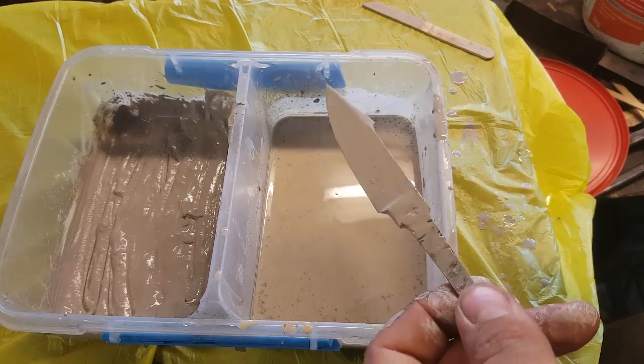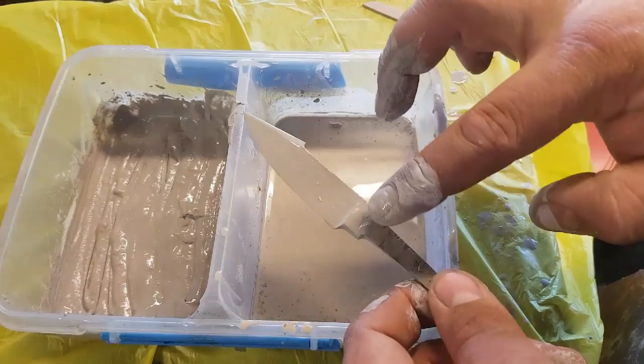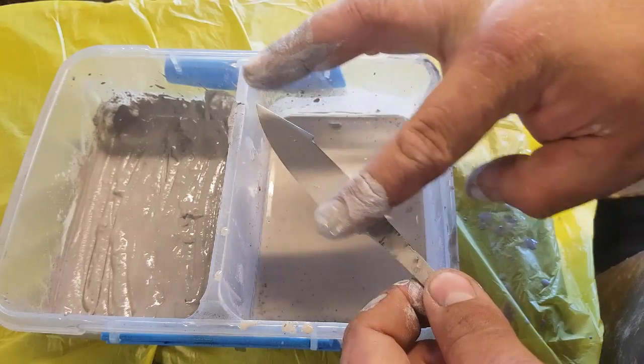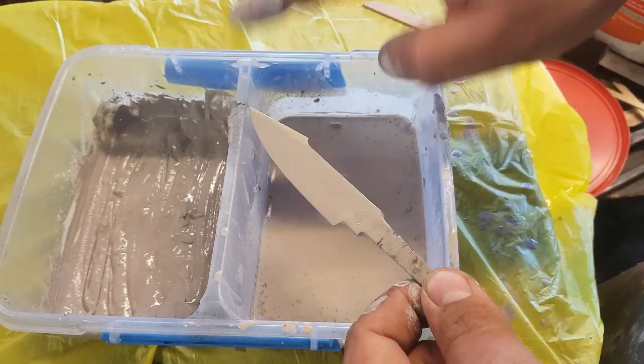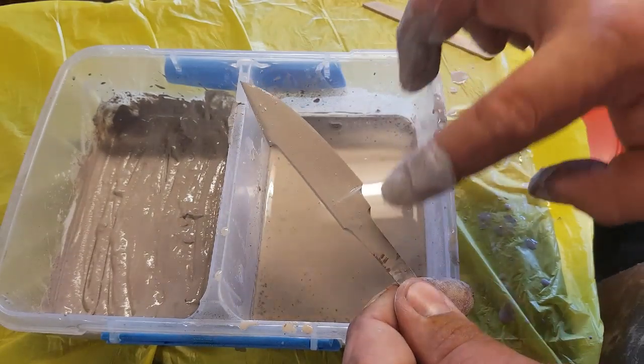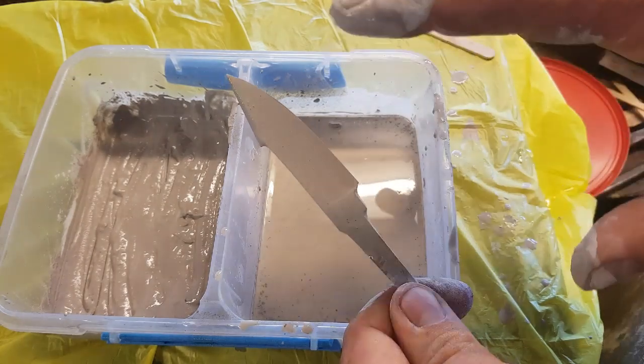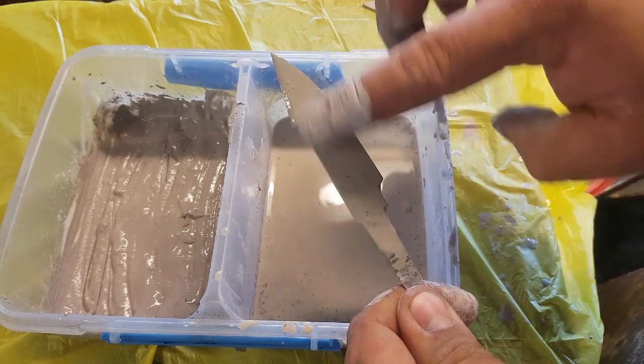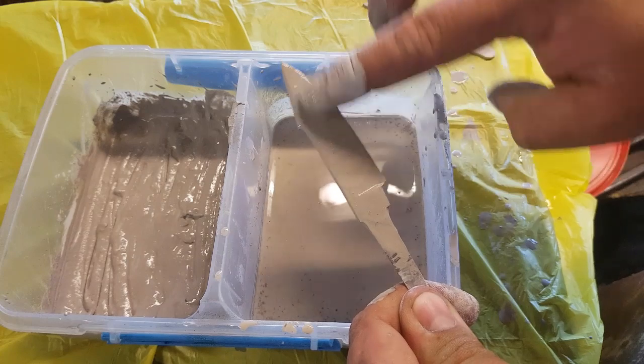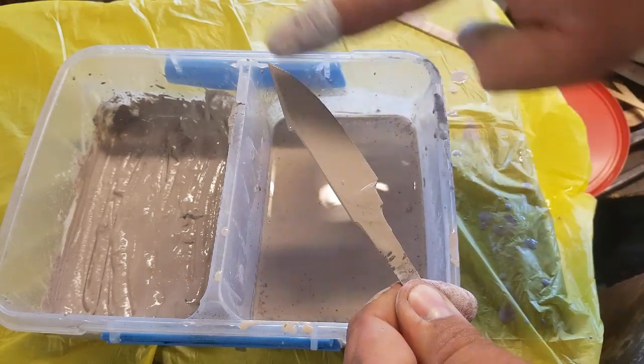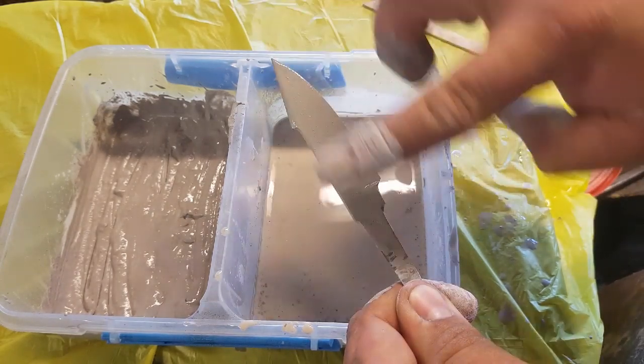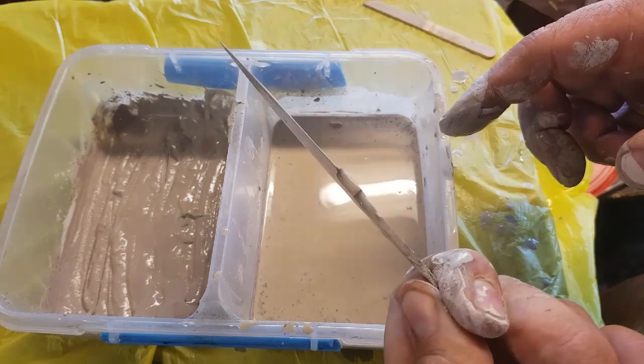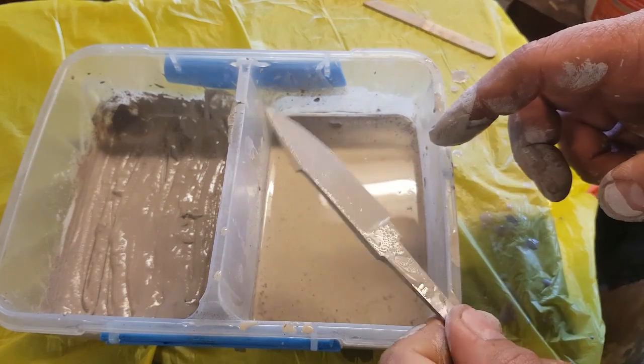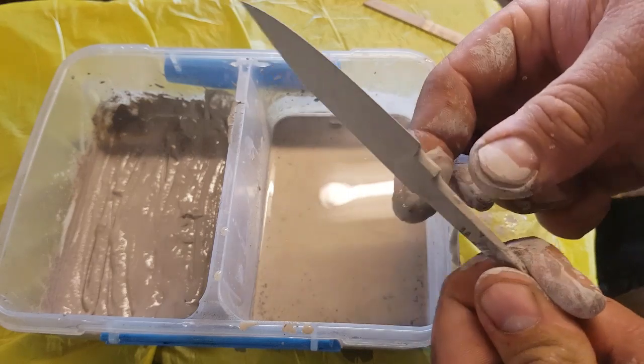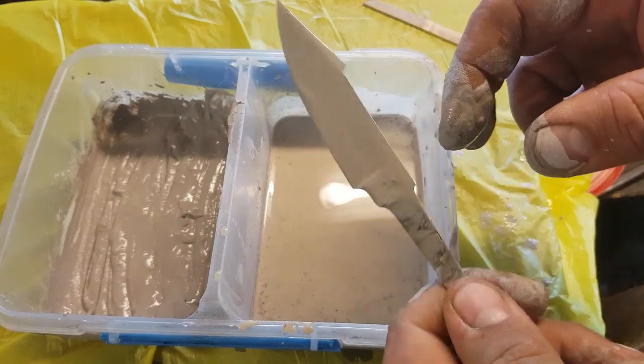Okay, so I've hit it with some degreaser and I've hit it with some paper towel, and as you can see, the clay is clinging to it really well now. I find that if you have any spots that are still not allowing the clay to stick, if you just abrade it with the clay using your finger, you can get it to cling perfectly and get a nice even coat. Now this is, again, a really thin coat. You're not actually making the Hamon at this stage. It should be thin and even all the way around.